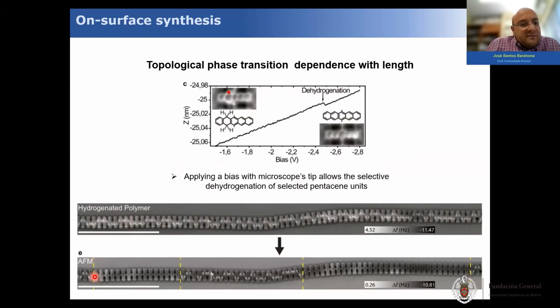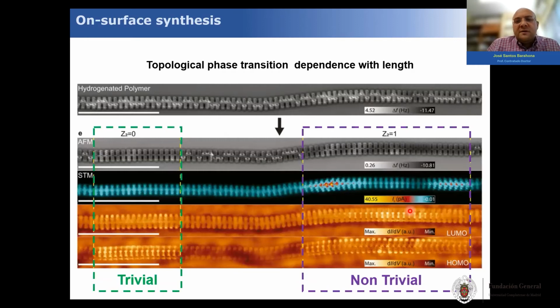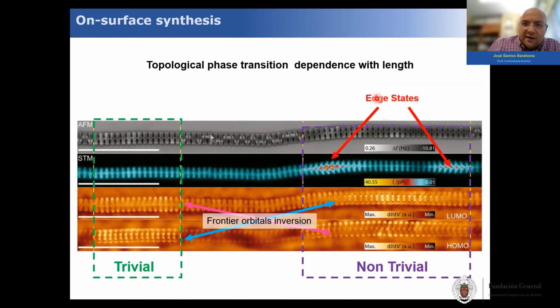We can engineer them by building segments of different lengths at will. So we prepare this segment, which is short, and this one, which is quite long. And then we can measure the orbitals by STM, and we can see that for the longer ones, once again, they become non-trivial, whereas the short ones are trivial. So in the non-trivial ones you see the edge states, and also, interestingly, you can see the frontier orbitals inversion. You can see here how the LUMO of the trivial becomes the HOMO of the non-trivial, and the very famous bow tie, which is the HOMO of the trivial, becomes the LUMO of the non-trivial.